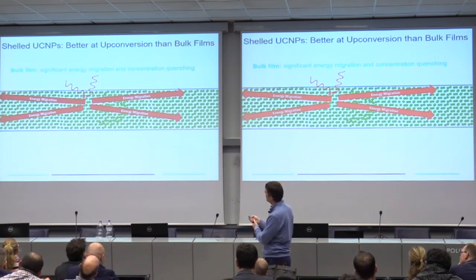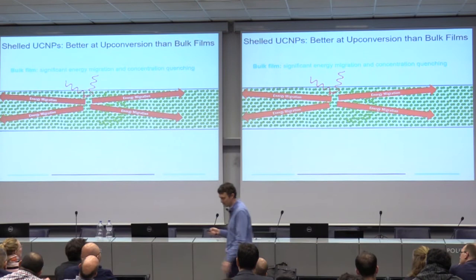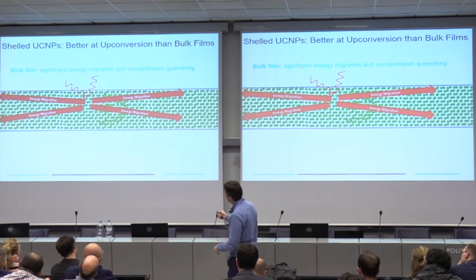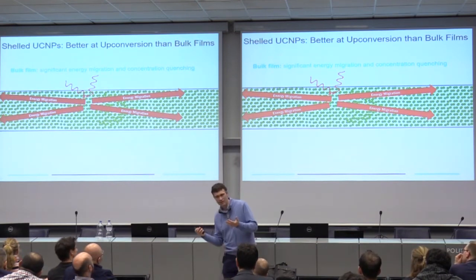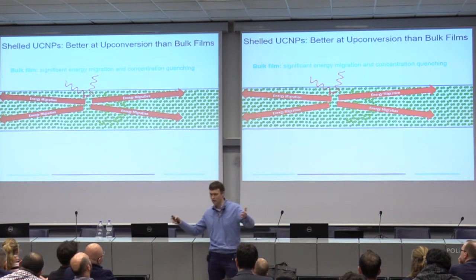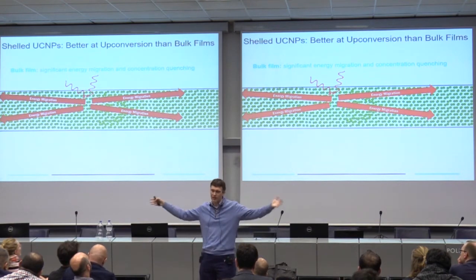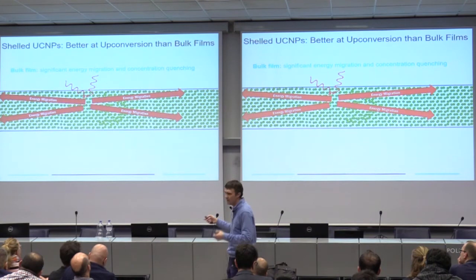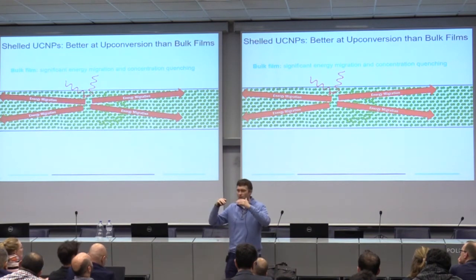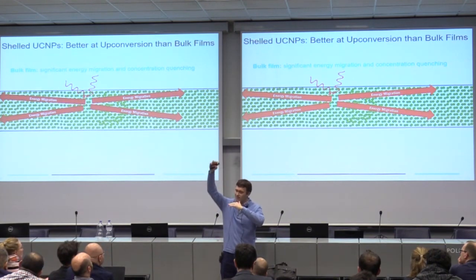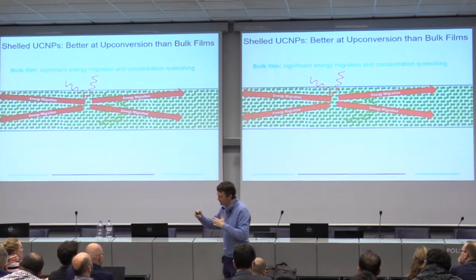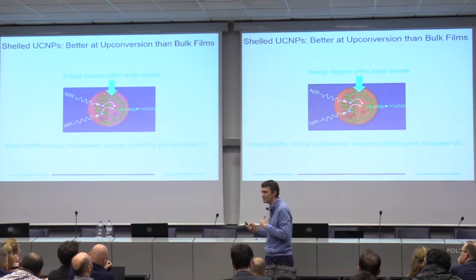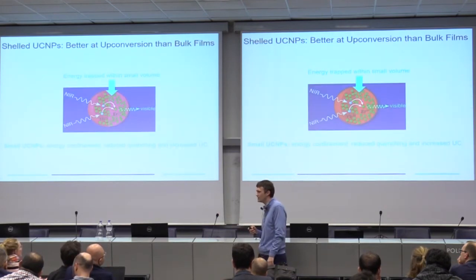So here's my cartoon of an upconverting bulk crystal. And so you shine your near-infrared photons onto here, and the near-infrared photons get absorbed, and they transfer their energy to an ion, and then that can just keep transferring energy to its ion. So your energy can migrate away rather than staying in the same ion and then climbing its excited state ladder to get to the upconverting states that you want to get. But if you force the energy to stay in a single particle, well, then it can actually be much more efficient at doing this upconversion.